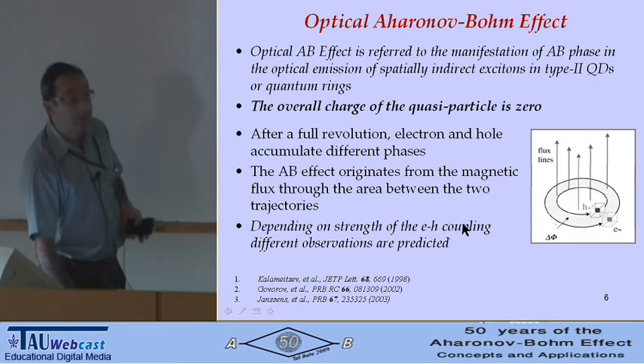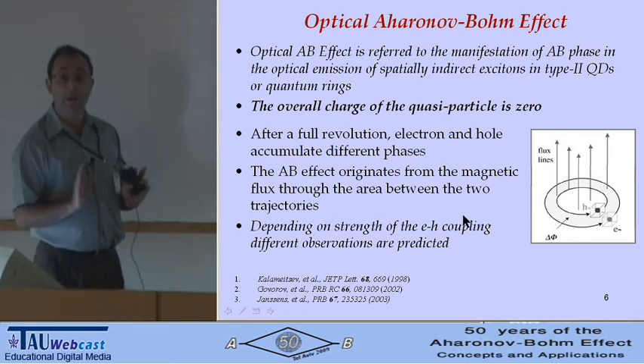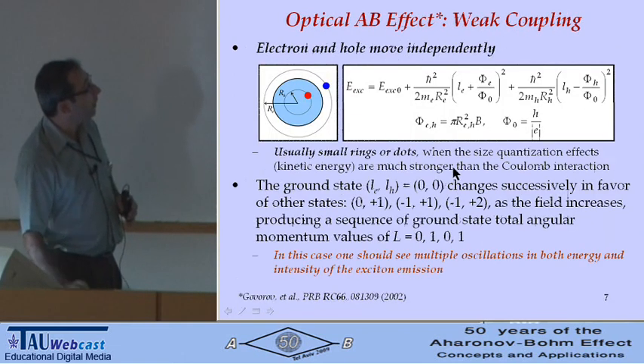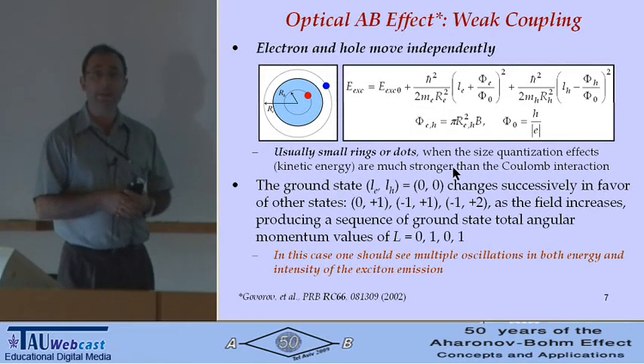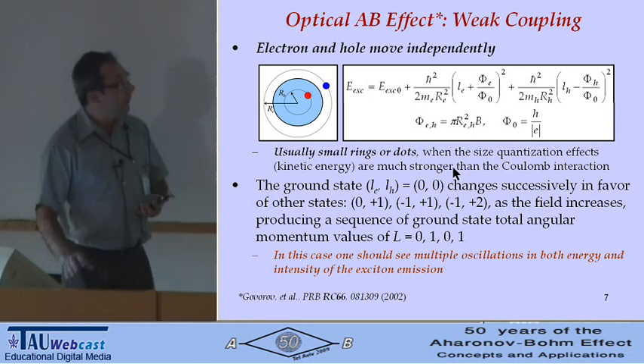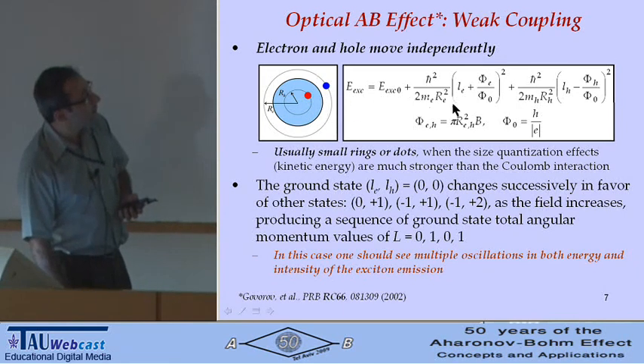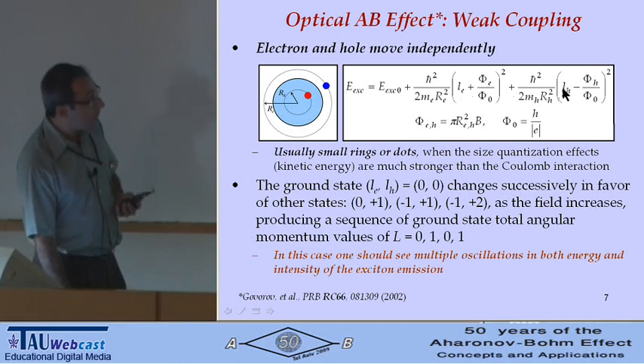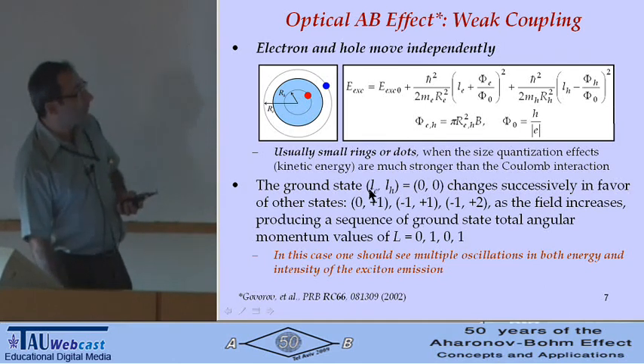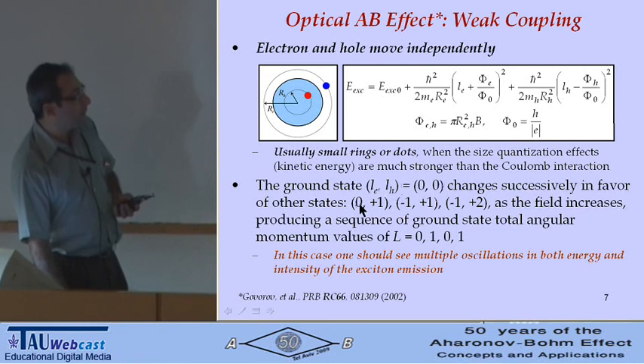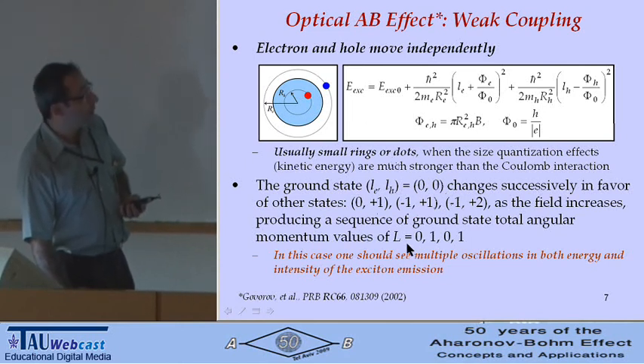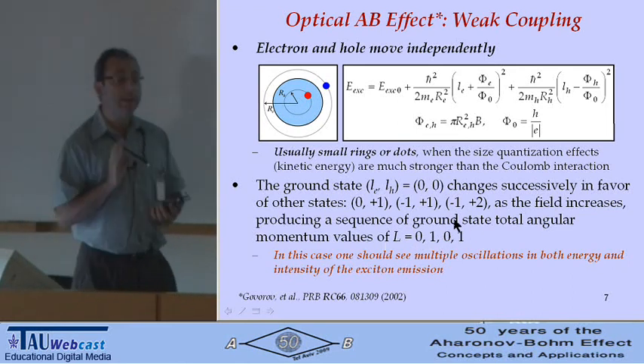And depending on the strength of the electron-hole coupling, you can have, theoretically, ideally, two cases. Case number one, when the electron and hole move independently. Basically, it's a single particle approximation. So you can write the excitonic energy in this form, for the electron orbital momentum and the hole orbital momentum independent. What is interesting in this case is that the ground state will change sequentially from 0 plus 1, minus 1 plus 1, minus 1 plus 2, and so on. That means the total orbital momentum of the electron-hole pair will be changing from 0, 1, 0, 1, 0, 1, and so on. Why is that important?